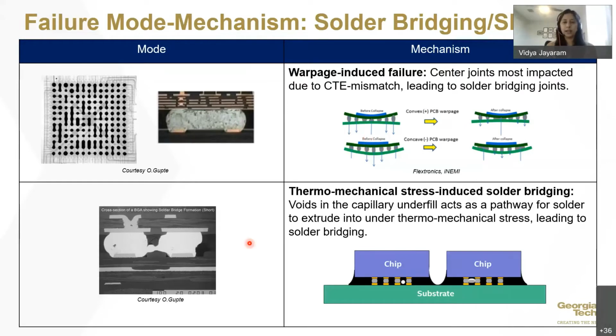Another thermomechanically induced stress that leads to solder bridging could be if there are voids in the capillary underfill that is present between the solder joints. This can cause the solder to extrude into the void when it experiences a thermomechanical stress or repeated heating and cooling, for example. So the solder can extrude into the voids, and that can also lead to bump bridging.